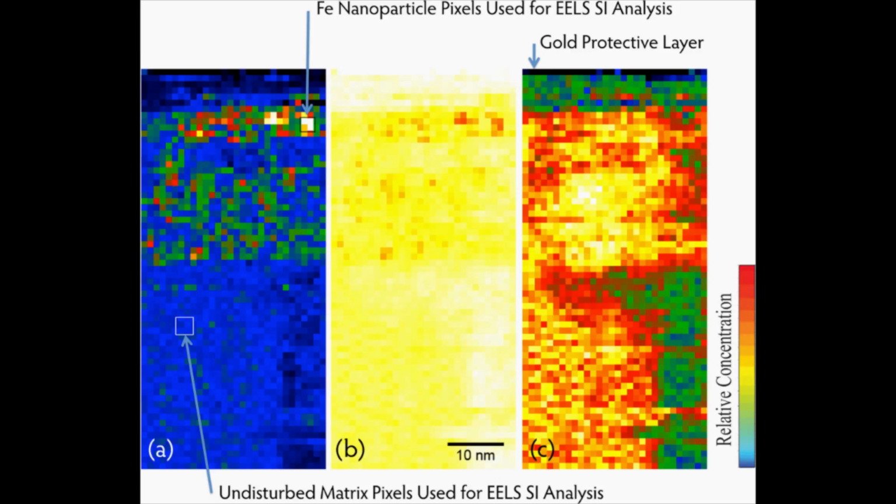Consider this map of the distribution of the most important elements within a section of the orthopyroxene sample when exposed to helium. From left to right, concentrations of iron, oxygen, and magnesium are given. Nanophase iron is indicated by spots of higher relative concentrations of iron and lower relative concentrations of oxygen.